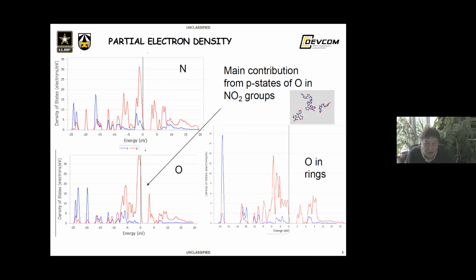What about the electronic structure of the LLM-172 crystal? Important information about chemically active atoms in the crystal may be given by calculation of the partial density of electron states. From the plot, one may see that the major contribution to the region near the highest occupied states comes from oxygen from nitro groups. I'm not sure you can see here, but this is about 20, this is about 10, and this is about two, this oxygen from the rings.